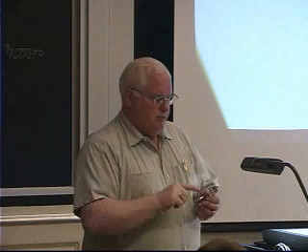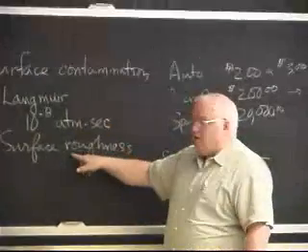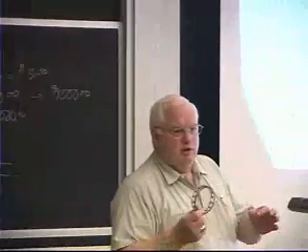The aluminum makes a nice bearing surface, and in fact, most of the bearings in an engine, the rod bearings and the main bearings on the crankshaft, typically are the same type of aluminum to steel cold bond. They take a sheet of steel or a big long roll of steel, and a big long roll of aluminum. They clean them as well as they can, typically an acid clean and a surface wire brush. They actually roughen up the surface for reasons we'll talk about. And then they squeeze them together with tremendous pressure and start rolling them and extending them, making a joint. Now, it's not a perfect joint, but it's good enough for the bearings.